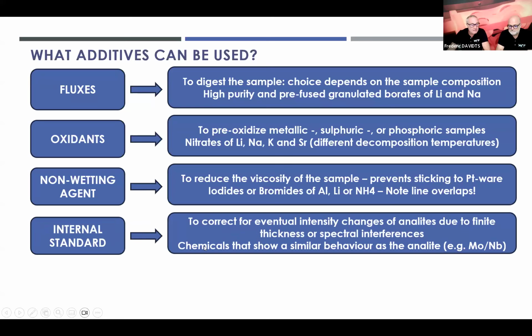Internal standards may also be used. These internal standards can be used to correct for eventual intensity changes of analytes due to the finite thickness of the sample, or maybe also due to spectral interferences. Important is that we use chemicals that show a similar behavior as the element that we want to analyze. So if we want to analyze, for example, molybdenum, then niobium is an ideal element to use as an internal standard for molybdenum.